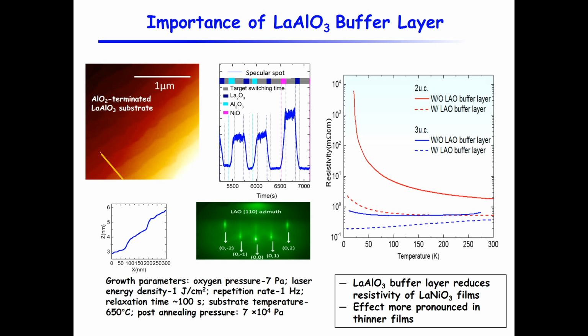What we have also found is that we need to grow a buffer layer of lanthanum aluminate. Because we found that however well you treat your substrate, there are recipes that you can use to treat these, but it's not good enough. You need to first put some homoepitaxial lanthanum aluminate buffer layer before you grow the lanthanum nickelate.